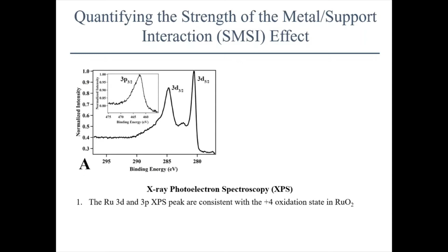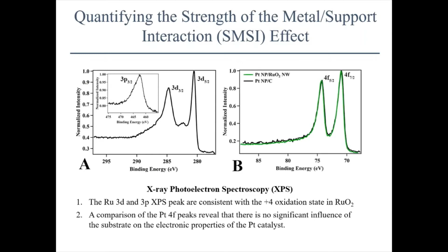When we did XPS, we saw that the ruthenium was in the +4 oxidation state from the ruthenium 3d and 3p peaks and their positions. But what was more interesting was the positions of the platinum 4f peaks. We took our platinum nanoparticle on carbon catalyst and our platinum nanoparticle on ruthenium oxide catalyst, took XPS in the platinum 4f region, and compared them. What we saw was kind of surprising. The peaks were essentially overlaid. So there wasn't a dramatic or intense interaction between the two such that the platinum electronic properties were so different that it led to an XPS shift. The catalysts were close enough that XPS could not distinguish the electronic properties of the two catalysts.